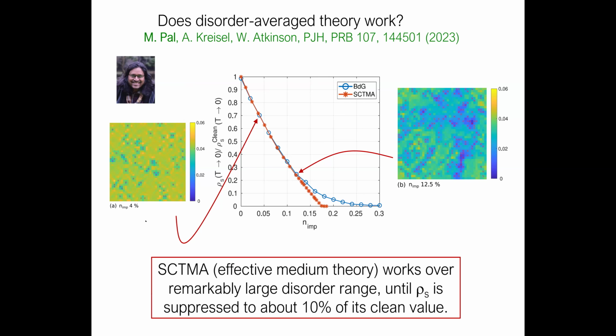And the nice thing is if you make the single assumption that yes, the inhomogeneity that we're worried about in cuprate samples is coming from disorder, and that the massive inhomogeneity that you see is probably due to the fact that the system, because it's close to the Mott insulating phase, is maybe close to a phase separation. And so these effects are all magnified in this strongly correlated system. We can simulate that with a Bogoliubov-de Gennes simulation where we put in some dopant atoms by hand. In this particular case, we took the impurity potential to be t, the hopping, which is a weak to intermediate strength potential, not a unitary scatterer for those who are interested.